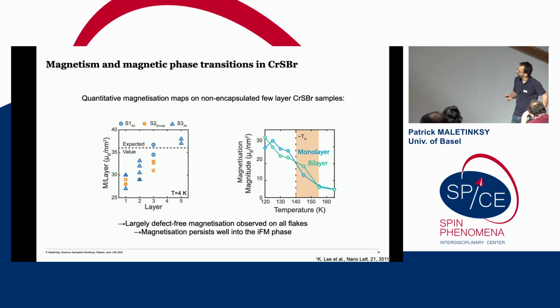We were also able to look at this magnetization as a function of temperature. Here you see two examples for a monolayer and a bilayer. Here going to this critical temperature of 140 degrees. So this is the Néel temperature where the correlation between adjacent layers vanishes. But we see that there's clearly still some magnetization remaining beyond that. And that's exactly this intralayer ferromagnetic phase that I mentioned before. Again, work is in progress to understand that further.